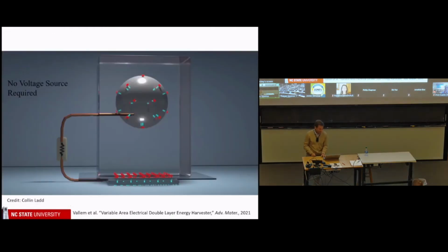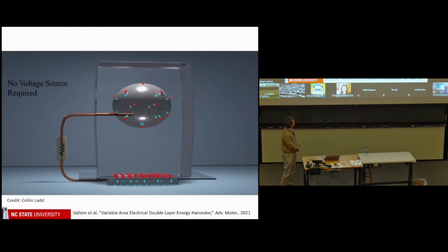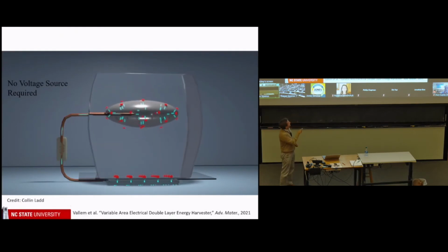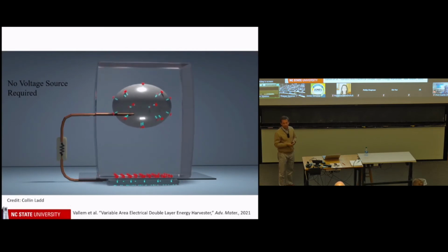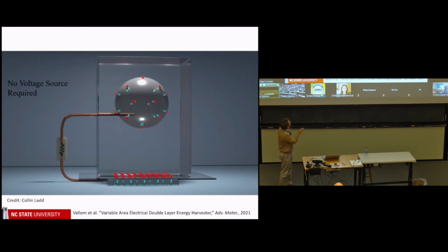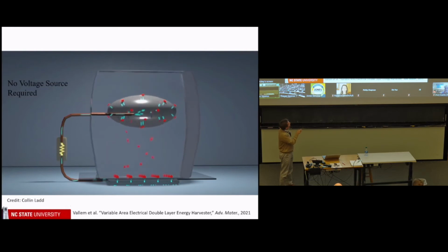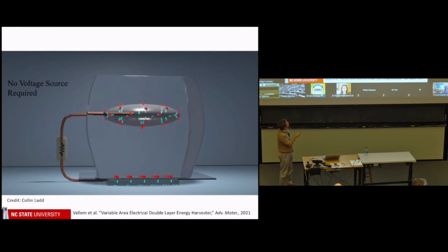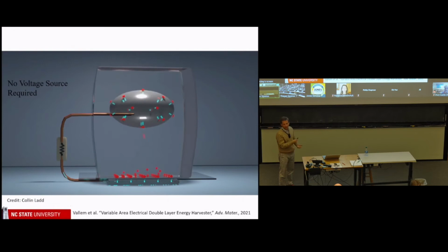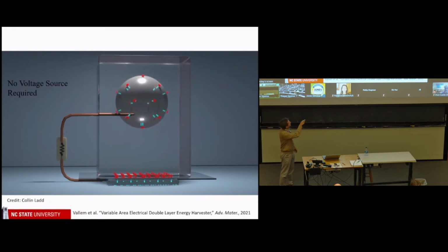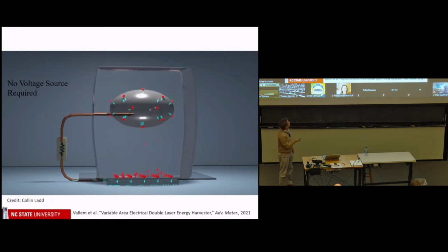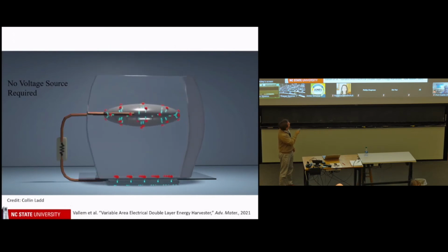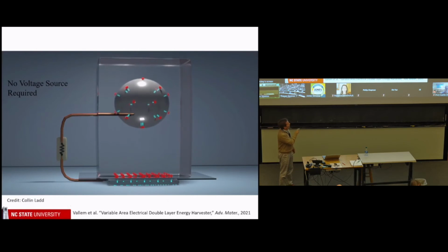So what we did, shown here in this little cartoon, conceptually, is take liquid metal and put it in a hydrogel, which is just a source of water. Jello is a hydrogel, right? It will naturally form an electrical double layer. When you squish it, like is being shown here, you change the area of your capacitor, where the capacitor is just the area of this liquid metal. When you do that, you pull charge from another capacitor because you disturb the electrical equilibrium. And when you let it go, those charges go back. So that's kind of the idea.